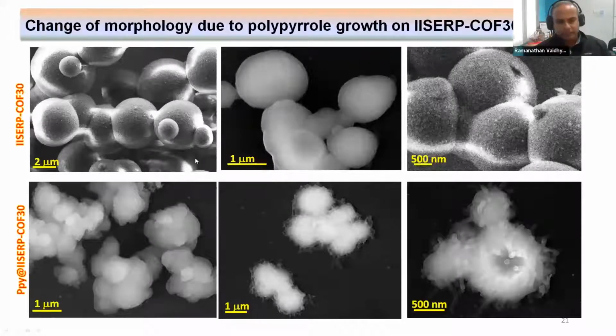And here is the SEM image of the neat COF versus the polypyrrole loaded COF. You can already start seeing the nano chains or the micro chains of the polypyrrole all over the COF. You can always argue whether it is inside the pore or outside the pore, but we go through a very thorough washing procedure using Soxhlet methods, which typically removes the polypyrrole chains which will be staying outside, which is soluble in selected solvents.